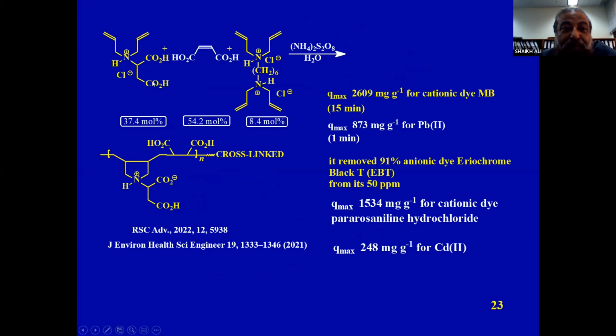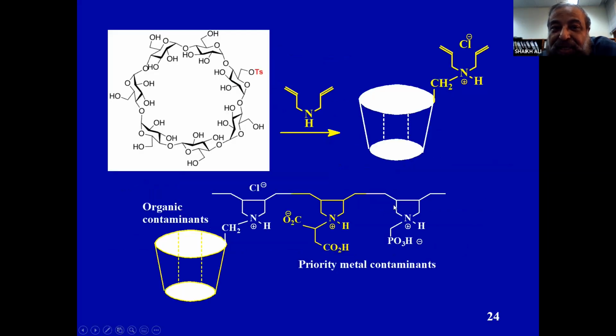Now here is another one, this is from aspartic acid, and you can see here, this is the maximum we got among all the resins we developed, 2,609 milligram. You can take activated charcoal and other things, they will hardly take 50 to 60 milligrams. But here, 2,609, and lead, it can take 873 milligram per gram. It can remove eriochrome black T 91%. This is an anionic dye, and it can remove a basic cationic dye, pararosaniline hydrochloride, 1,534 milligram per gram. So this is very nice.